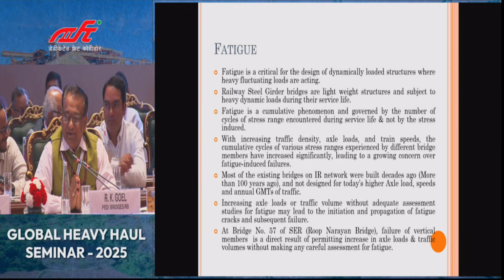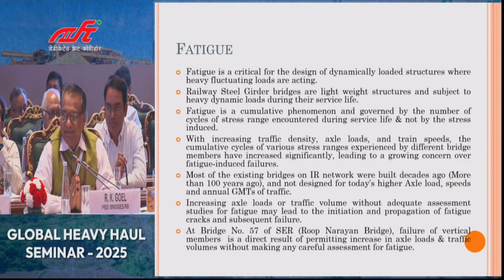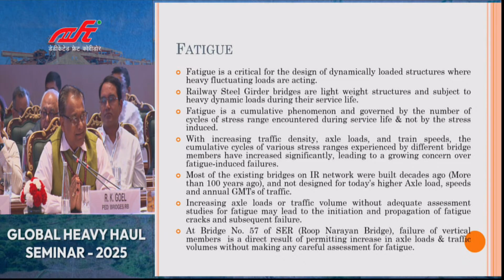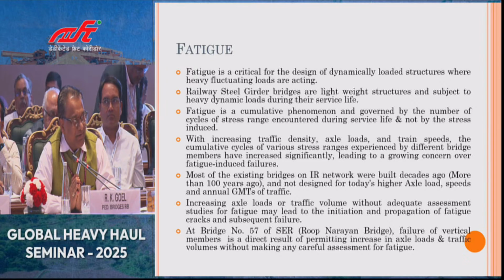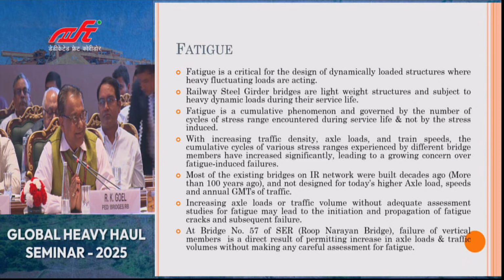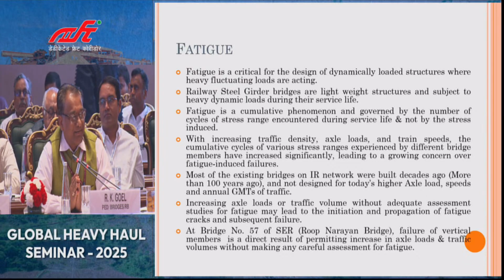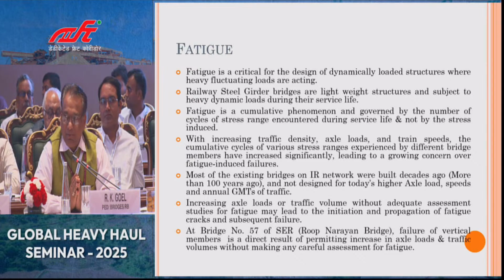Some of these old bridges were built more than 100 years ago when the axle loads were much less, up to 18-ton axle loads. And now we are having axle loads up to 25 ton. So there is a concern of fatigue. The way we are concerned about fatigue in rails, we take care of their testing, we do USFD testing, replace those rails, and there is a laid-down criterion of replacing rails after 800 GMTs. But somehow similar attention has not been given to bridges, particularly the steel girder bridges, which are to be designed and maintained with respect to the phenomenon of fatigue.